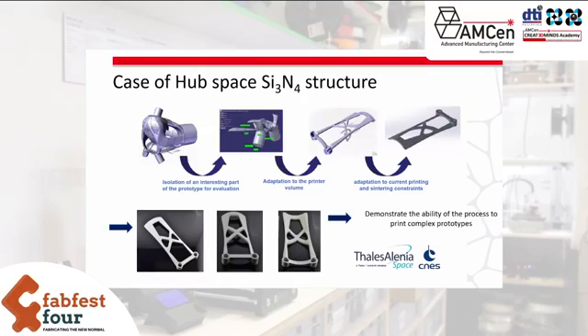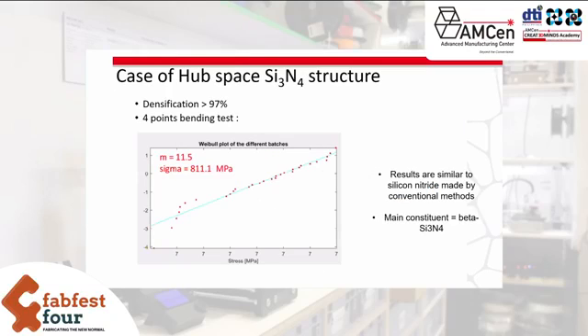To obtain a good quality of silicon nitride after printing and sintering is the final objective. This is why, still in collaboration with Thales Alenia Space, we print some beams in order to check the mechanical properties. After printing, sintering, and 4-point bending tests, we obtain very high density, as you can see on the graph, superior to 97%.